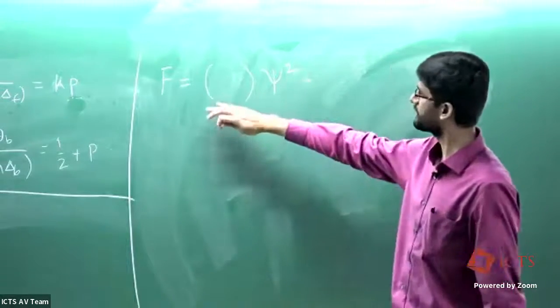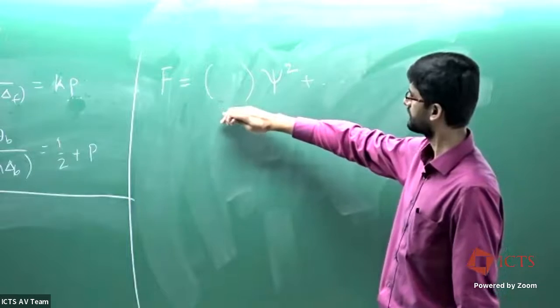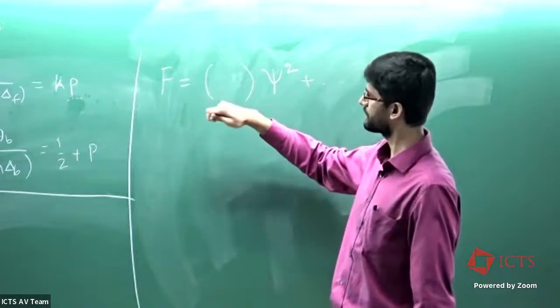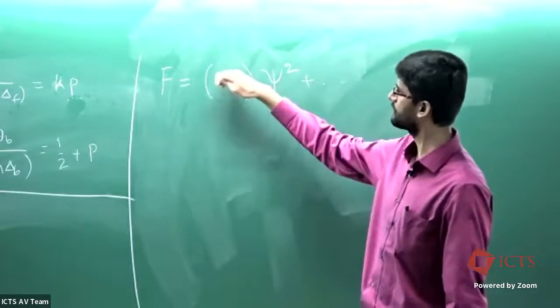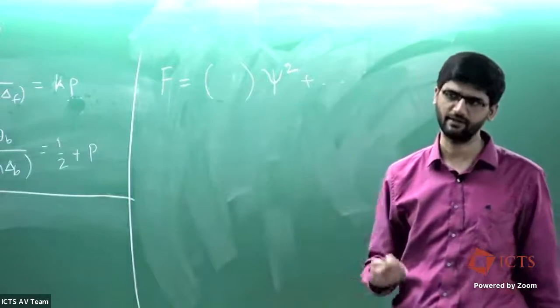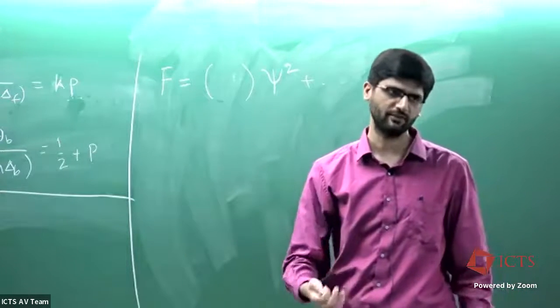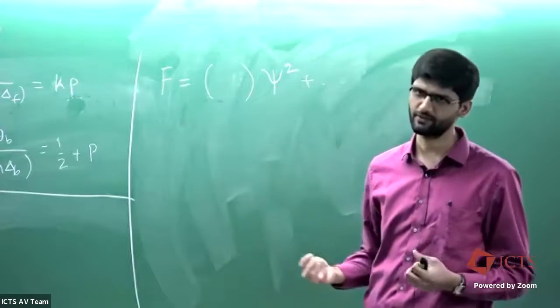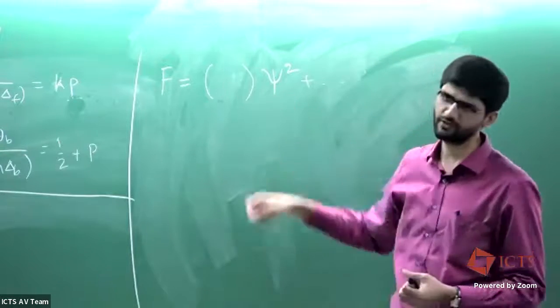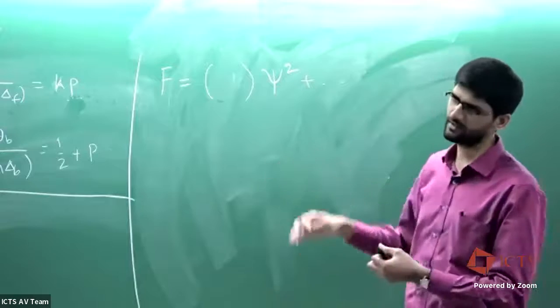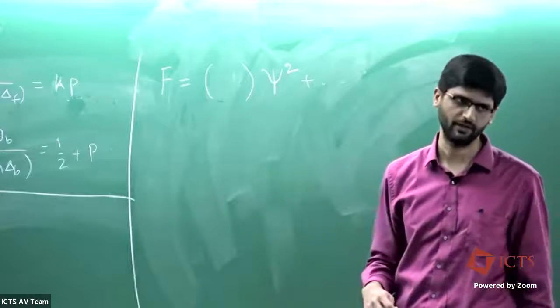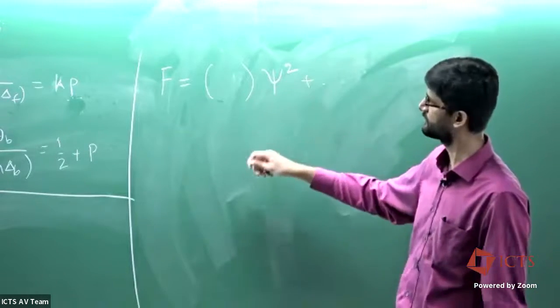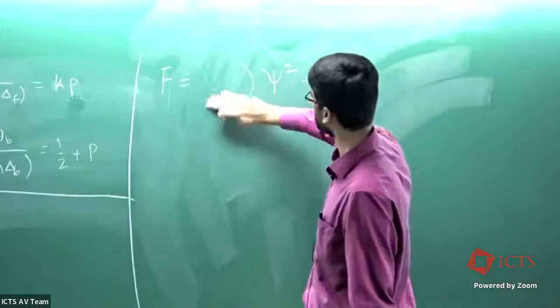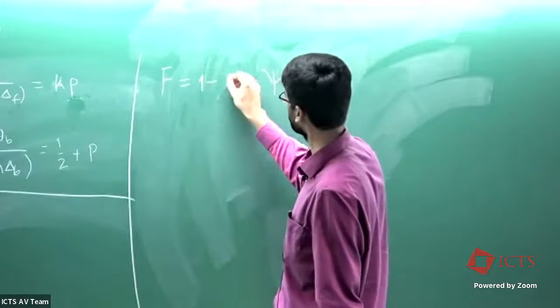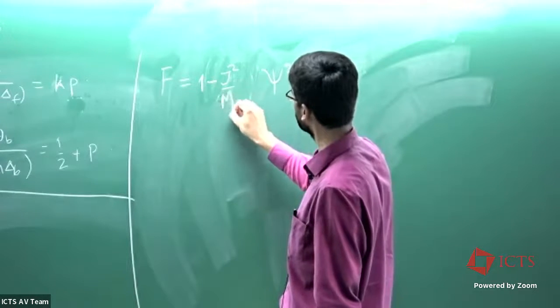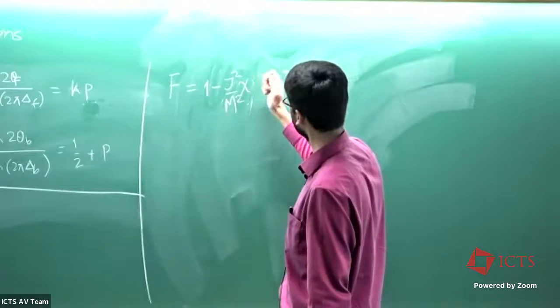But the important thing is that, just like a simple Ginzburg-Landau argument, if the coefficient of this quadratic term is negative, then you are in a spin glass phase. So you have a non-zero psi order parameter. If this coefficient is positive, then you are in a non-spin glass or an ordinary phase without any spin glass order parameter. And it turns out this coefficient is actually 1 minus j square over m square times the local susceptibility.